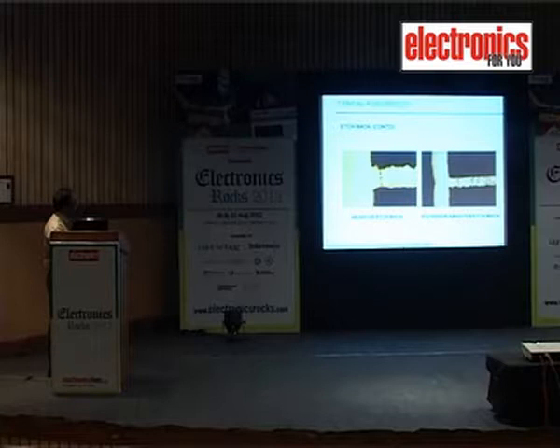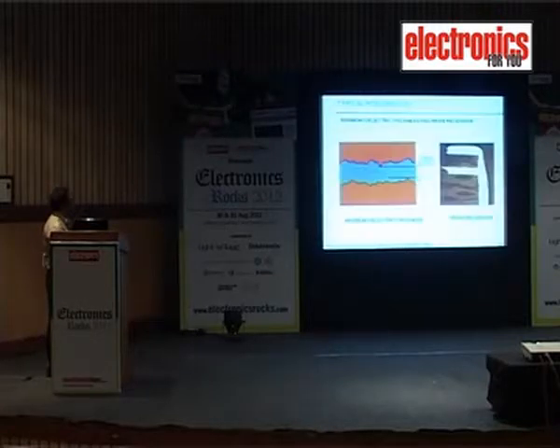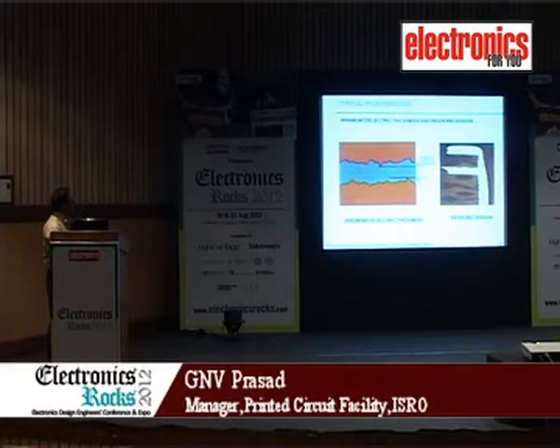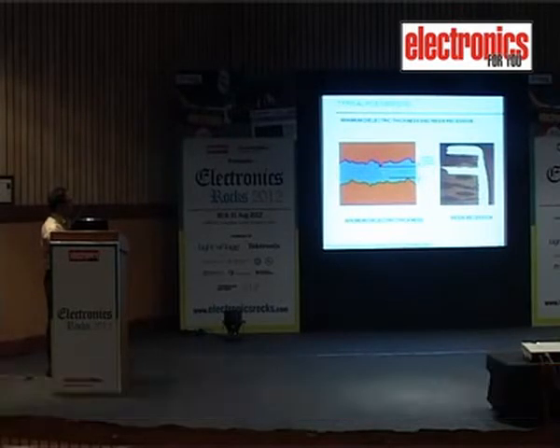You can see the demarcation line. Anytime when we subject it to thermal cycling, this will break and cause discontinuity of the hole wall. So excessive etchback and negative etchback are not desirable. And you can see the dielectric thickness. Because copper, when we process, can have slightly ragged edges, we critically view what the dielectric thickness is after the processing and see that the minimum is maintained as specified by QA guidelines.